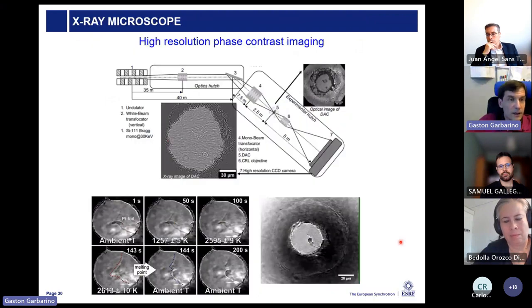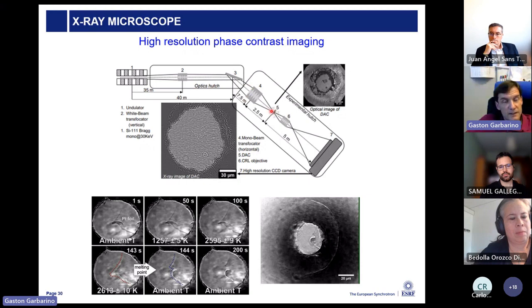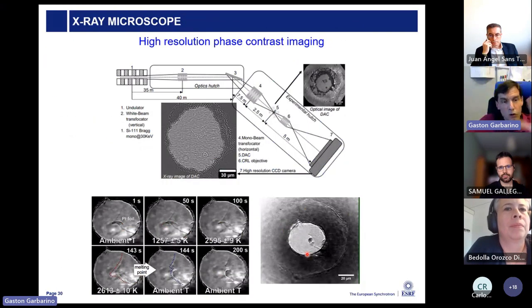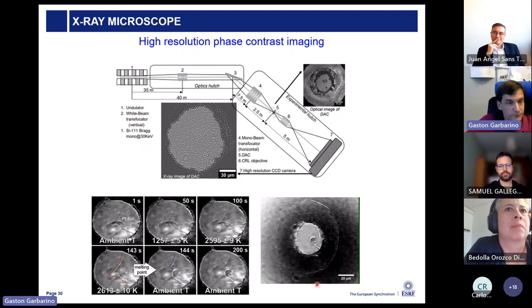At the same time, now we can put in some optics and have a beam that illuminates the full sample. As you can see here in the bottom part, we can do tomography of your sample. We cannot fully reconstruct because the cell has a certain opening, but we are able to do high resolution phase contrast imaging on the sample.